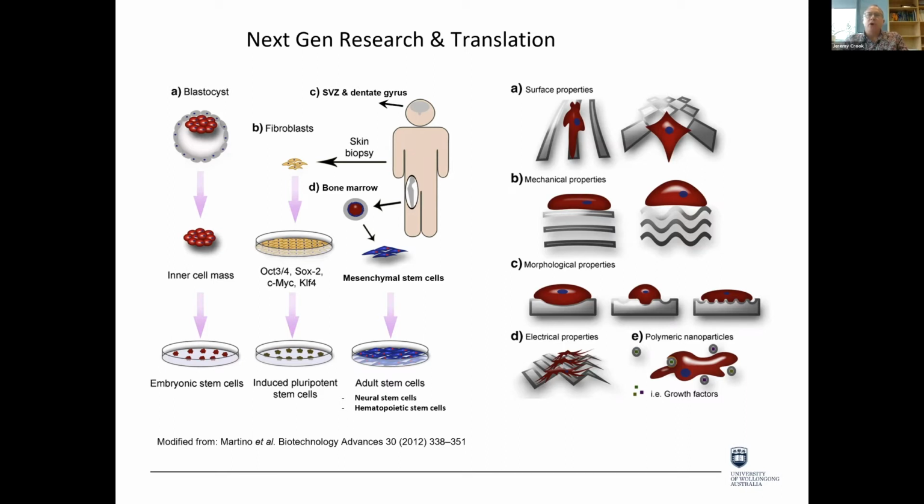And so a biopolymer will transmit specific signals to cells that are decoded into biochemical signals. Hence, as for other biomaterials, the surface topography, the modulus or the softness, the porosity, and even electrical properties of, for example, a hydrogel or conducting polymer influences cell survival and fate, the latter acting via material actuation or intracellular ion, for example, calcium influx.